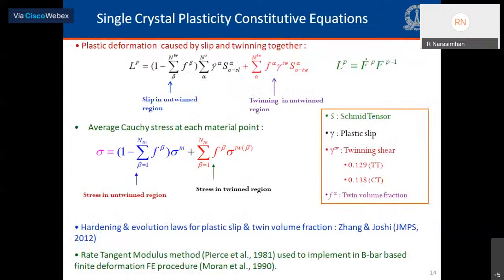The flow rule is written, as you can see in this slide, for the plastic part of the spatial velocity gradient, LP, given by the equation on the top of the slide, and it involves contributions from slip in the untwinned region, the first term on the right-hand side of this equation, and twinning in the untwinned region, which is the second term in the RHS. Now, in these equations, capital S represents the Schmid tensor, gamma is the plastic slip, gamma TW is the twinning shear, which is around 0.13 for extension twins, around 0.14 for contraction twins in the case of magnesium, and f alpha is the twin volume fraction.